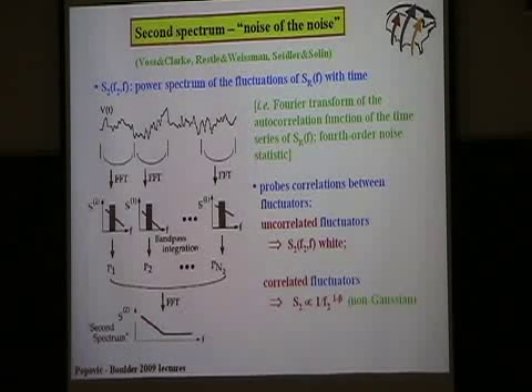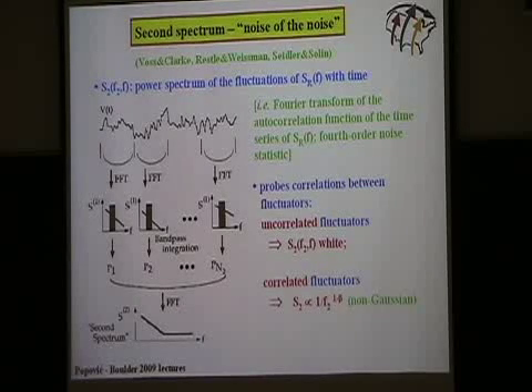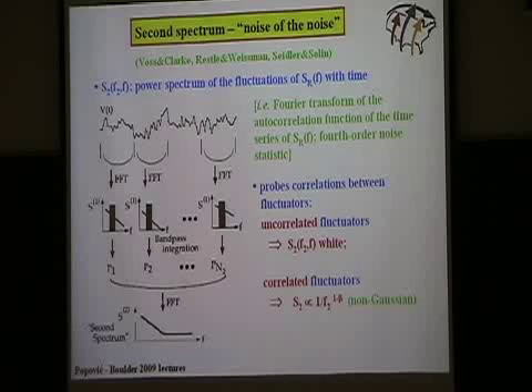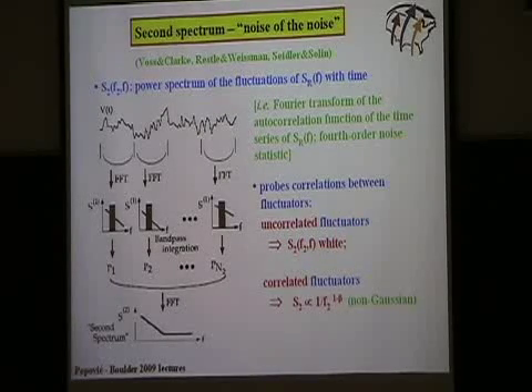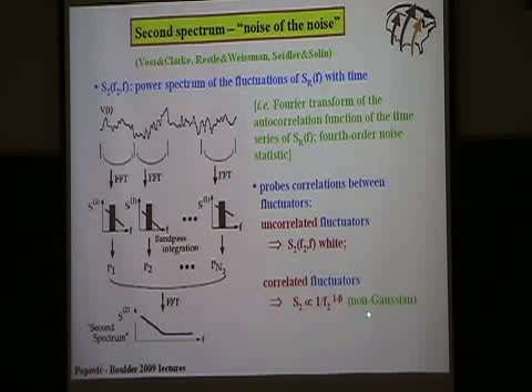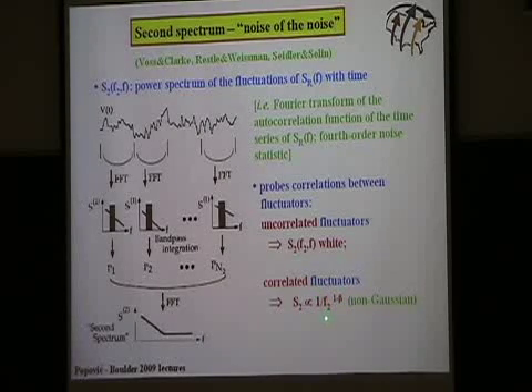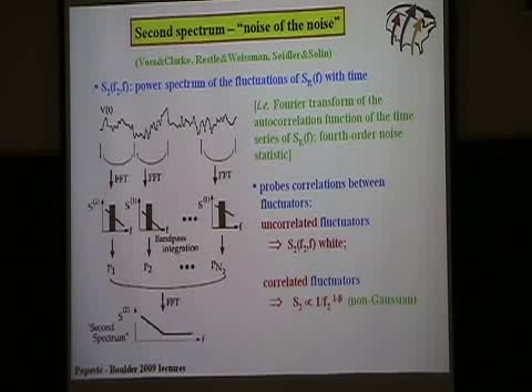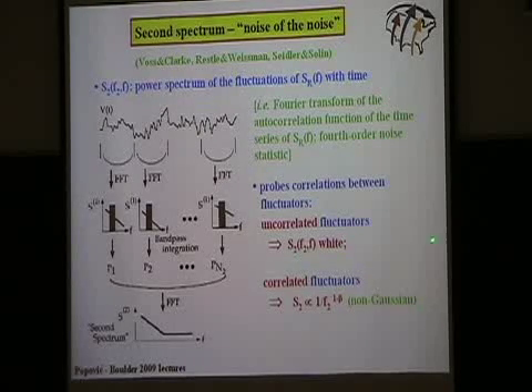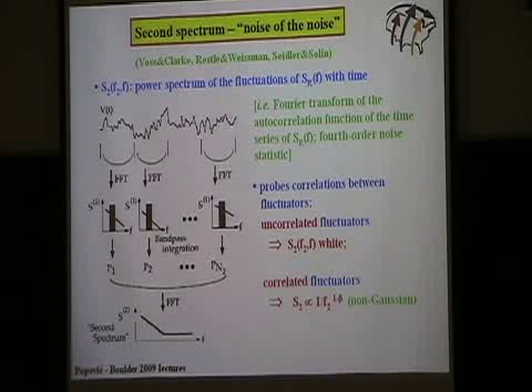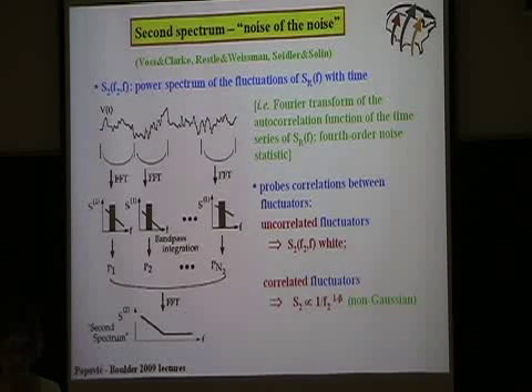If the fluctuators are uncorrelated, if you always get a contribution from the same states, then this will be essentially the same. Maybe you have a Gaussian distribution because you have a finite number of data points, but the spectrum of that should be white. On the other hand, if different states contribute as a function of time, then the second spectrum will also be 1/f type with some exponent that people call 1 minus beta. So the main point to remember is that this 1 minus beta is a measure of the correlations. If there are no correlations, 1 minus beta is 0, and if you have some, then it's bigger than 0.